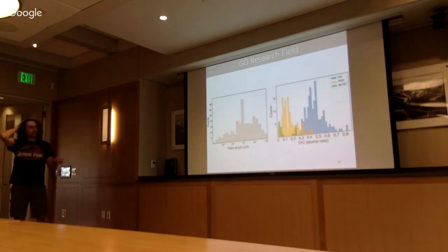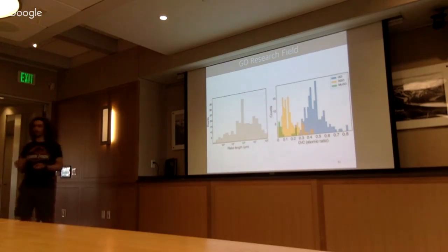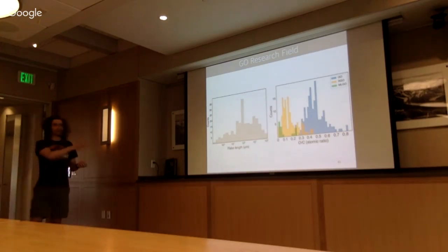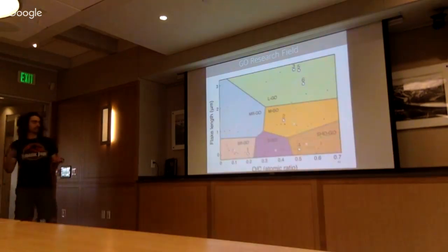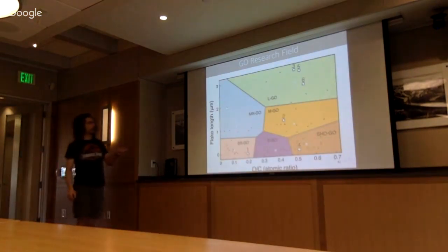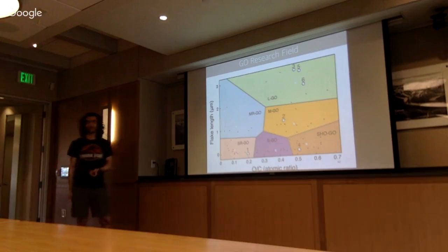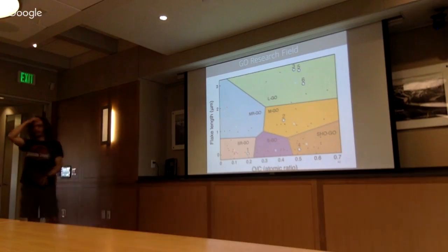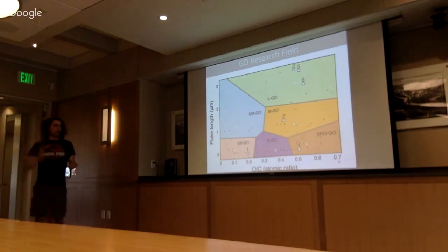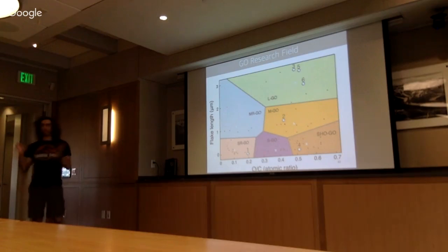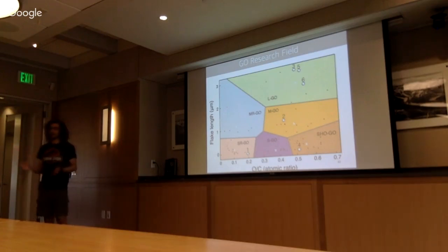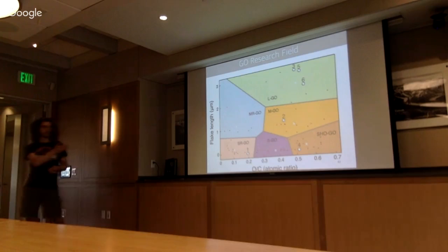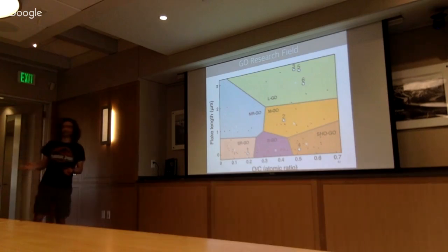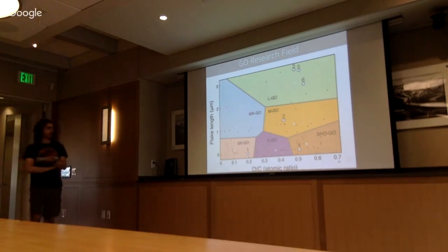So we did something else. For papers that were reporting both the morphology and the chemistry, we plotted them into a space. Each of these dots is a scientific publication, and we ran a clustering algorithm. And what we could see here is that there is not just one kind of graphene oxide, but with 6 classes, we were explaining 90% of the variance in the field.